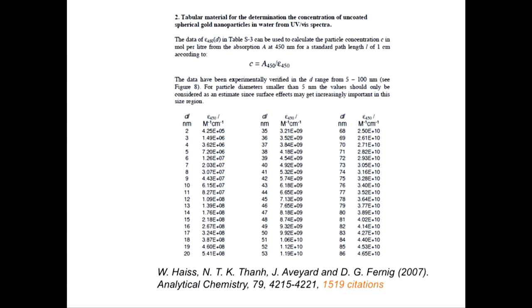Then you need to determine the concentration of the gold nanoparticle. First, you know the size of the nanoparticle from the previous table, and then you determine the extinction coefficient using this table. Then you can use a simple equation: the absorption at 450, divided by the extinction coefficient, gives you the concentration of the gold nanoparticle.